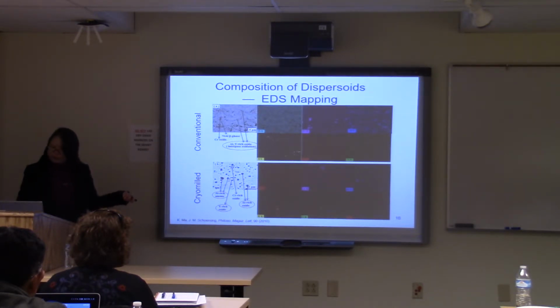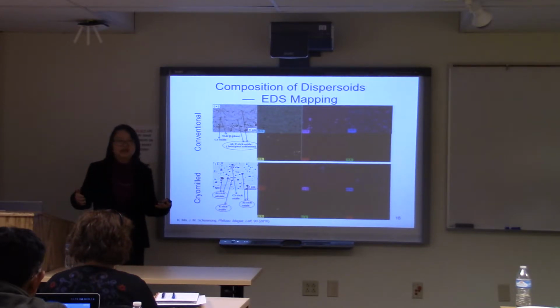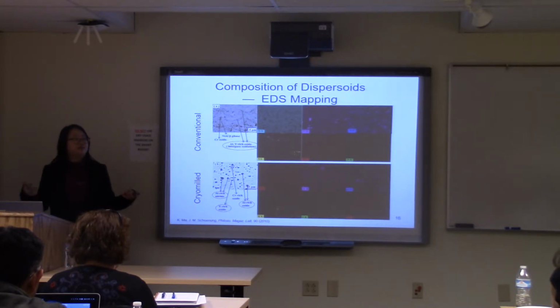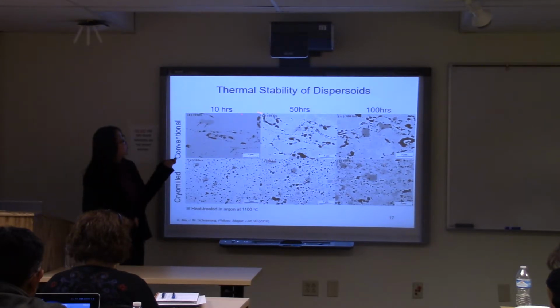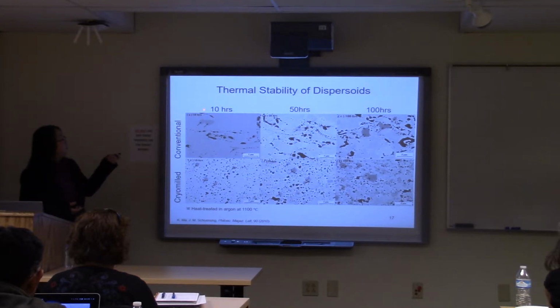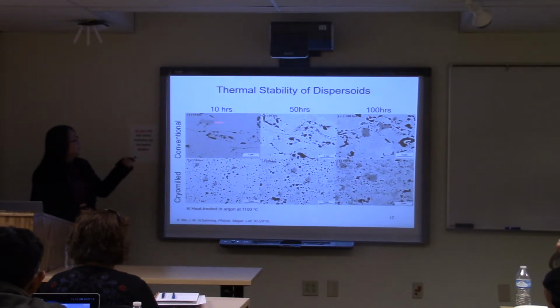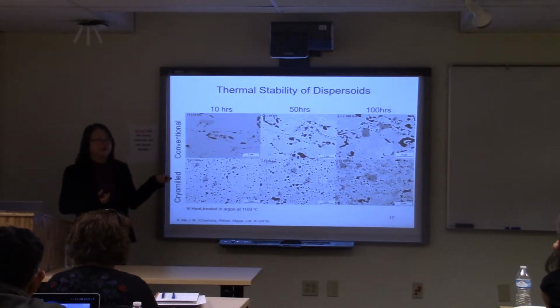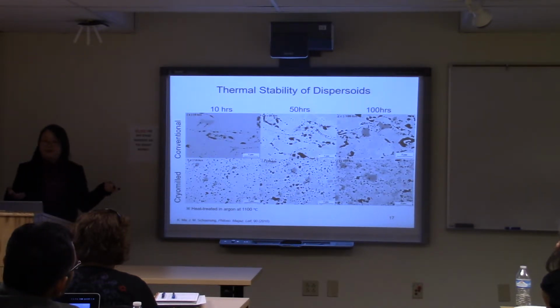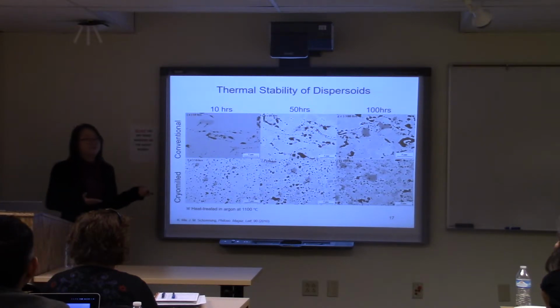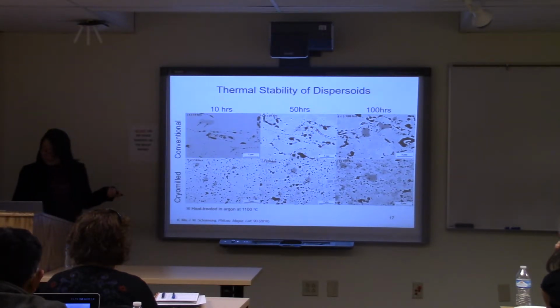Now we wonder, since thermal barrier coatings are used at high temperatures and for a long thermal exposure, will those microstructures be stable after a long time of thermal exposure? So I also studied the thermostability of these dispersoids. I heated the whole coating system at 1100 degrees C for different times. You will see there is a little bit of growth in the dispersoids, but the distribution stays the same. So I'm very confident to say those microstructural features are very thermally stable.